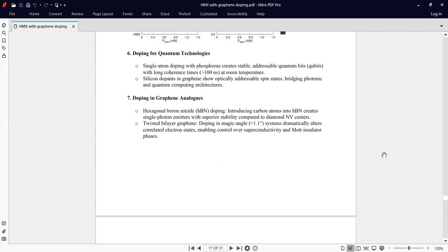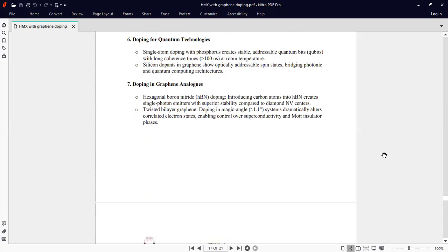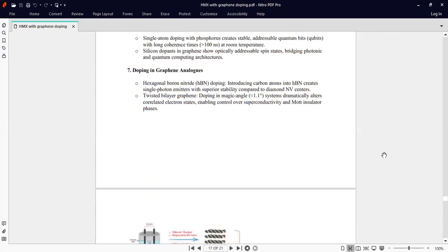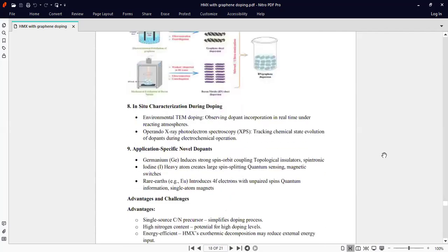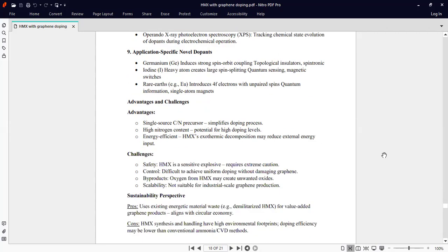Doping for quantum technologies: a single atom doped with phosphorus creates stable addressable quantum bits with long coherence times at room temperature. Doping in graphene analogues: hexagonal boron nitride doping, introducing carbon atoms into hBN, creates single photon emitters with superior stability. Twisted bilayer graphene: doping in magic angle systems dramatically alters correlated electron states, enabling control over superconductivity and Mott insulator phases. In situ characterization during doping: environmental TEM, observing dopant incorporation in real time under reacting atmospheres.